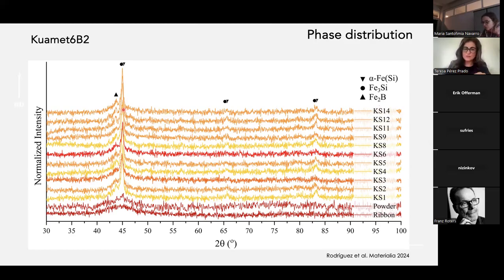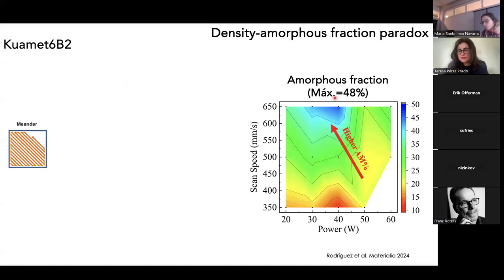Let us be a little bit more quantitative. By X-ray, we cannot distinguish exactly what is the structure of this phase. It could be an iron silicon phase, but we don't know if it's ordered or a disordered solid solution. We can do that later by other methods. And there is also some minor fraction of borides. With the help of the team in Saarland, we measured the amorphous fraction by differential scanning calorimetry. And this is what I show in this color map here.